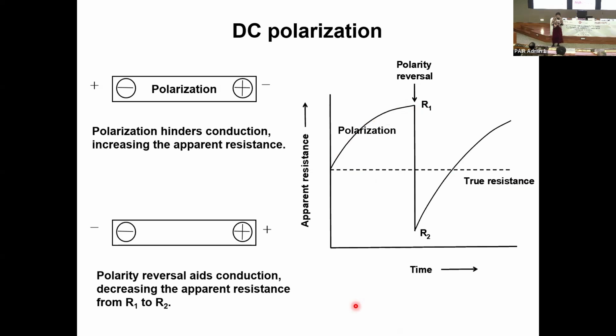The apparent resistance increases. But if you suddenly reverse the polarity, the polarization doesn't reverse instantaneously. So you get to a situation here where the polarization actually aids conduction. As a result, the apparent resistance decreases abruptly upon polarity reversal from R1 to R2. Okay?